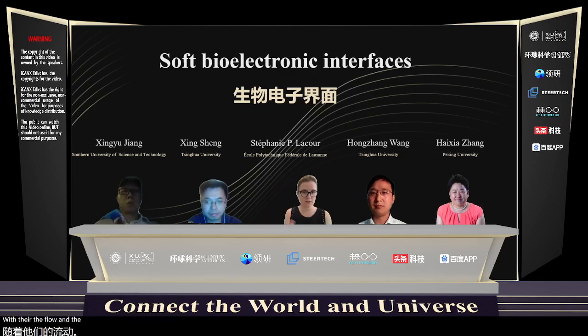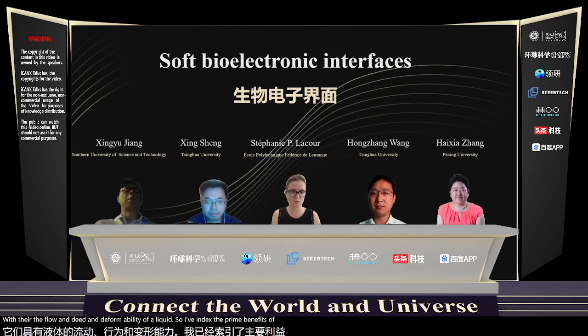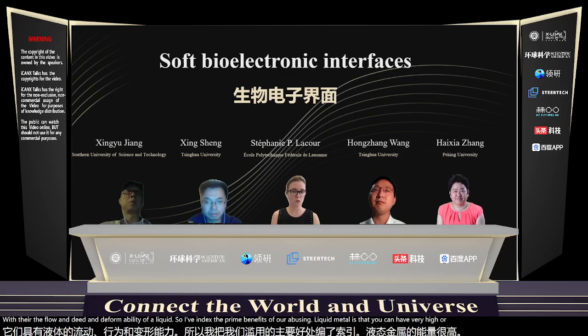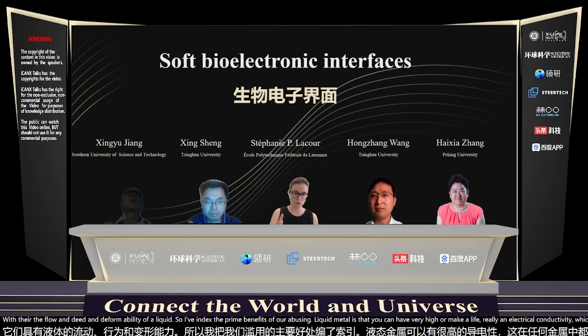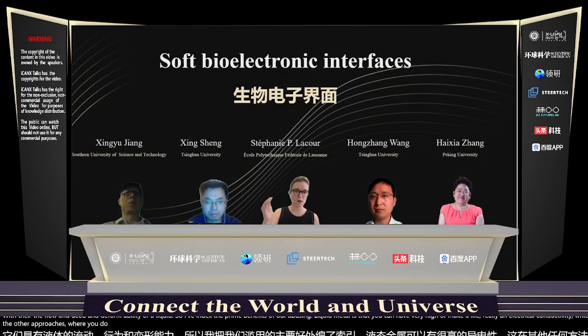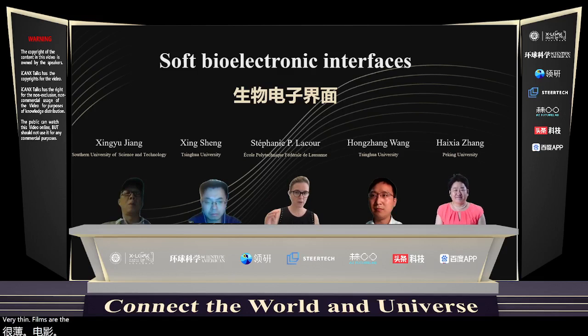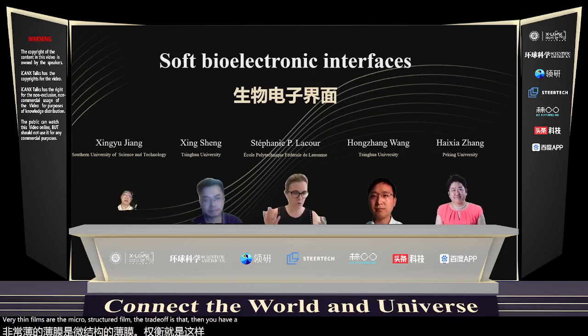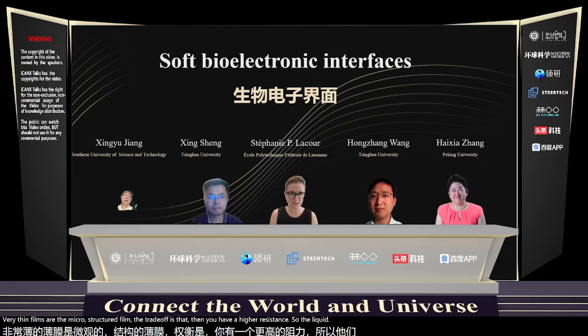So I think that's the prime benefit of using liquid metal, is that you can have very high, really metal-like electrical conductivity, which you don't really have in any of the other approaches, because the other approaches are where you do very thin films or the microstructured film. The trade-off is that then you have a higher resistance. So the liquid metal in that sense is an interesting approach.